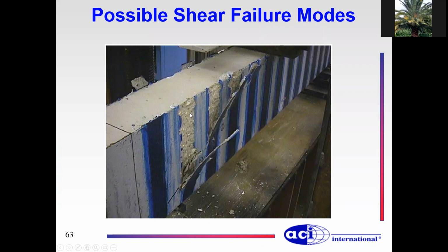You never get, very, very seldom do you get the delamination of the strip, or the laminate, or the sheet, or whatever. You don't get this failure at the epoxy line. The tensile strength of the epoxy is much higher than the tensile strength of the concrete. So your weakest point is the concrete. So what you do is that you pull concrete when failure happens like that.